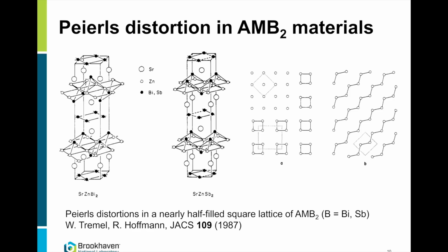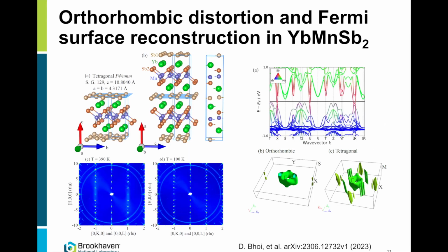So I gave up reading this paper 2 times before I finally finished it, after looking up who this Hoffman is. It turns out he is a Nobel Prize winner in chemistry. And then I realized, yes, that's exactly what we observe. So they predicted it, and at the time they predicted it, only one material was known to them to show this zigzag distortion, which is the Peierls transition in 2 dimensions, and it was believed to crystallize in that phase.